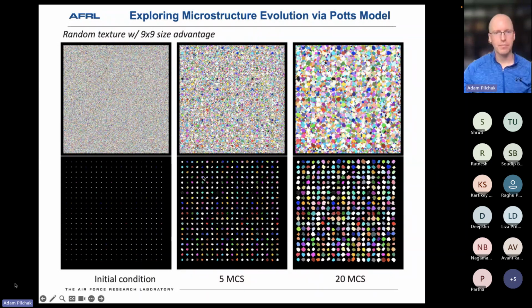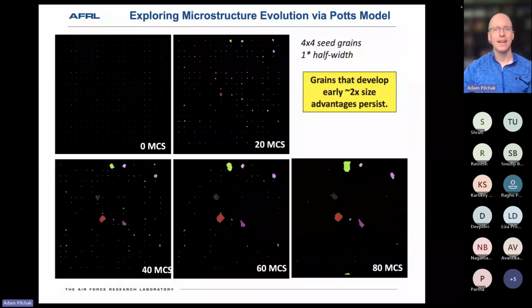As we evolve the system, in this case, because there's such a large size advantage, every single one of the seed grains ends up staying, and it persists through many, many more Monte Carlo steps until they ultimately impinge on one another and again transition to that curvature-controlled grain growth. The 9x9 case is nice to explain what we did, but not super interesting.